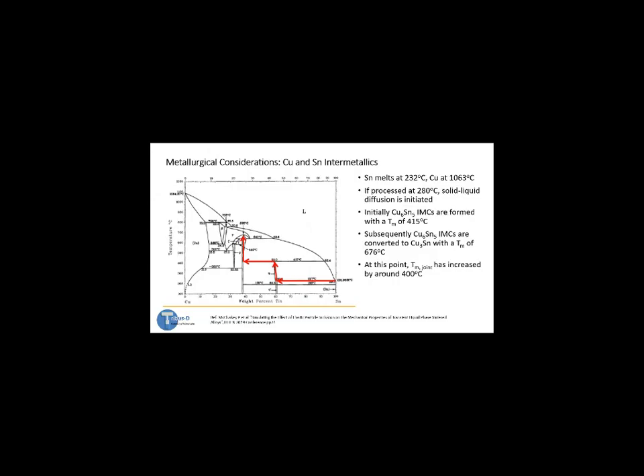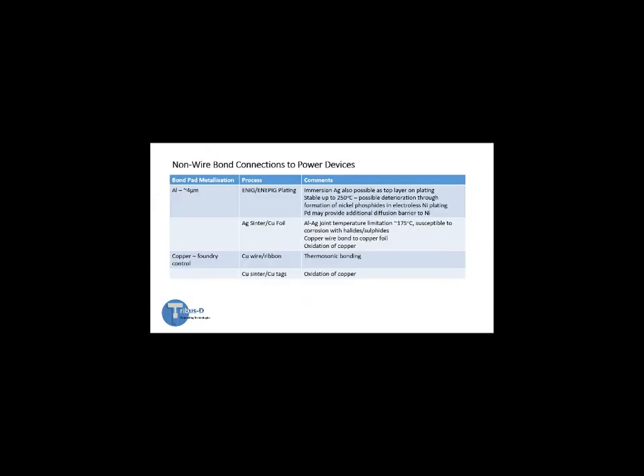And this is just an example from the phase diagram of where you go through doing that through different heating and temperature endurances, and you can, let's say, achieve from tin at 232 degrees C melting point, compounds which are relatively stable at 676 degrees C, but in all these things, the intermetallics still grow. They still may be brittle, and there still may be voids in terms of doing that.